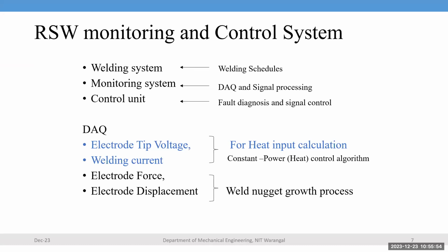The DAQ records electrode voltage and welding current, how much welding current you are supplying in a cycle. Is there any variation during the cycle, since the resistance is going to change? Then how much force you are applying, and what the electrode displacement is, because every time it may not be aligned with the bottom of the electrode, the alignment may change. Due to that, there will be a change in the nugget growth process.